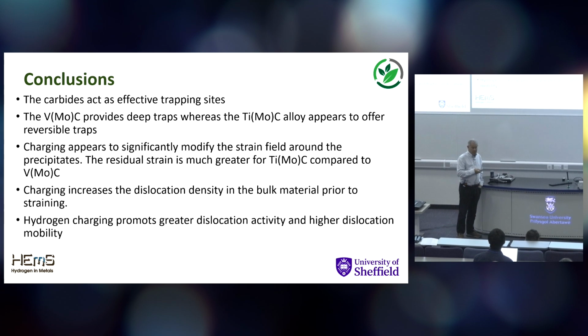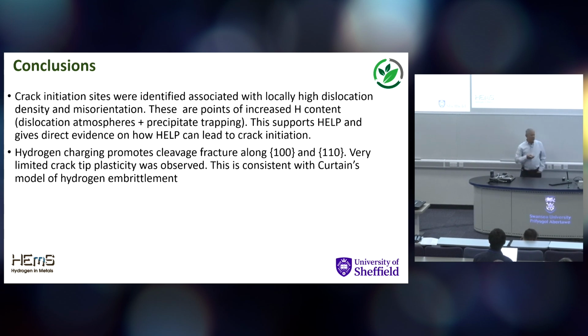The charging itself modifies the microstructure, increases high dislocation density and residual strain, and the strain field around precipitates is modified, and also the dislocation mobility. And as I've said, I think this points towards a HELP mechanism for the initiation, and is consistent with Curtin et al.'s model of hydrogen induced crack propagation.